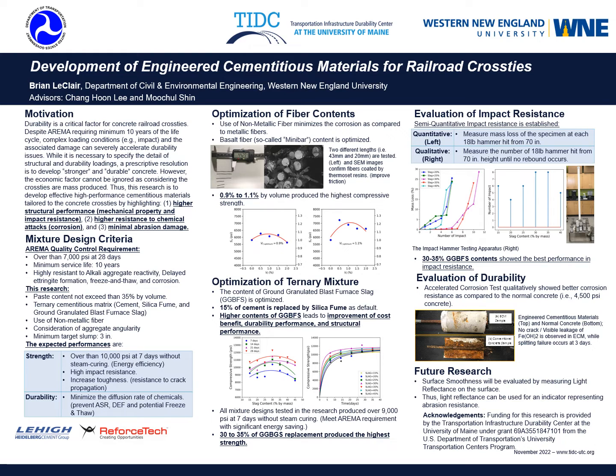To start, we wanted to find the optimal amount and length of non-metallic fiber. The fiber we used is basalt fiber. We use basalt because it is resistant to corrosion, unlike metallic fibers. Both graphs here in the top middle are fiber content versus compressive strength of the fiber reinforced concrete samples made. The one on the left is for the longer fiber, which is about 43 millimeters in length, and the right graph is the short 20 millimeter fibers. As you can see, we found 0.9% fiber optimal for the long fibers and 1.1% optimal for the short fibers. You can also see that the short fiber samples perform better across the board as opposed to the long fibers. This gave us the idea that about 1% of volume for short fibers is best for our purposes.